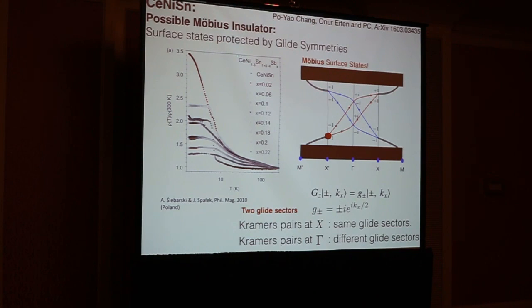And so here's cerium nickel tin, which is a semi-metal. If you put antimony in it, notice it develops this plateau. And there's lots of arguments over what this plateau is due to, but the simplest explanation is it's probably got surface states. And there are other examples of this, these kinds of behavior. There's cerium 343, and these may be wide examples of states which can be examined for interesting behavior.